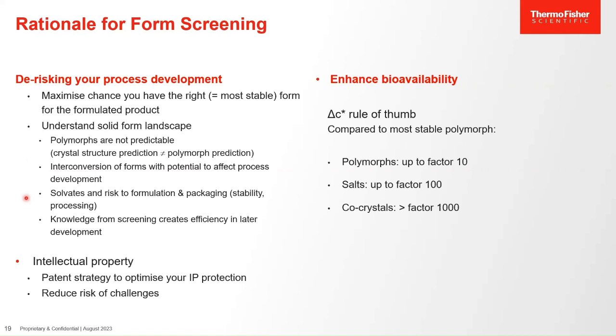Identifying solvates is important because solvates are generally a risk, both to process development, they may not dry easily, and to formulation. Solvates are usually not stable. There are very few APIs that are formulated as hydrates, for example, and most are anhydrous phases. And there is a good reason for that, namely their stability.